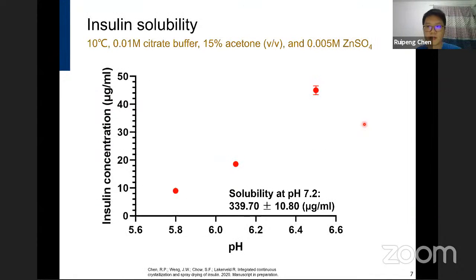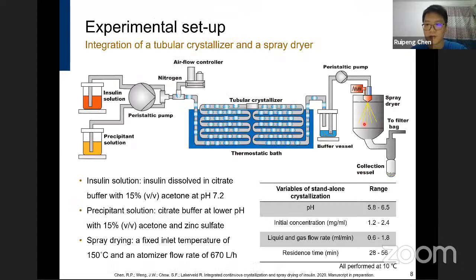Actually, we conducted some preliminary experiments, which were operated at a very low flow rate. And in those cases, we did observe the clogging and plugging of the system. But later, we increased the flow rate. And for the tested conditions in this operating range, at a liquid and gas flow rate of 0.6 or 1.8 milliliter per minute, we did not see clogging or plugging of the system.